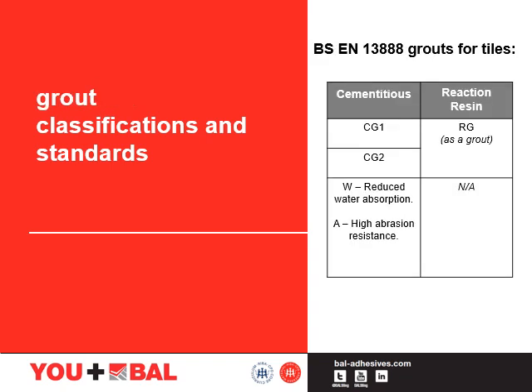Grout classifications and standards. In this section we have cementitious and reaction resin. Cementitious is normally, again, a bag of powder, and reaction resin is normally a 2 or 3 part product which you mix together, which is either a resin, a hardener and a colour, or a resin with a hardener and colour mixed together. The cementitious grout has 2 categories: 1, which is a basic grout, and 2, which is an improved or polymer modified grout.